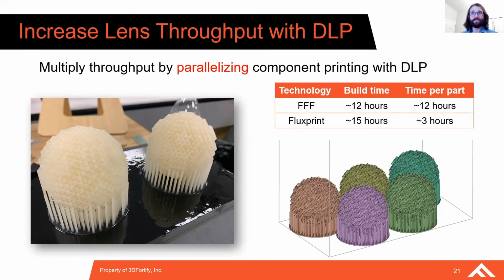Considering the parallelization capabilities of DLP, device throughput impressively accelerates as DLP cures entire cross-sections of a build plate in a single exposure using a projected UV light mask. 1 part or 5 parts will print at the same rate, providing that they can fit on the build platform. In the case of the 62 millimeter diameter Luneburg lens, we can fit 5 lenses on the build plate at a time. With a build time of about 15 hours, the throughput is roughly 3 hours per lens.